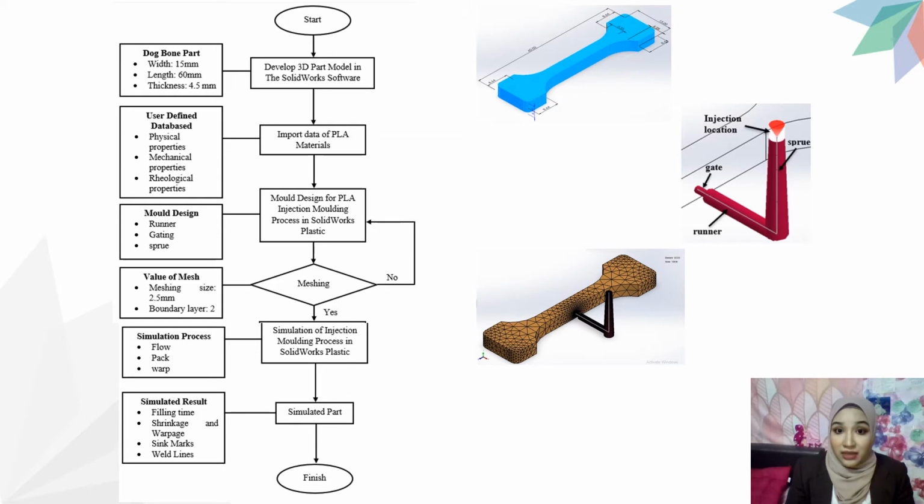The Solidworks Plastics simulation is used to analyze the plastic filling process and the parameters of plastic injection molding, which influence the quality of the product created using the plastic injection molding method. In this simulation process, the injection parameters such as injection temperature, injection pressure, and mold temperature were selected before starting the process. Flow plus Pack analysis was selected to simulate the injection molding process to obtain the material's flow behavior such as filling time, seam marks, volumetric shrinkage, and weld line.